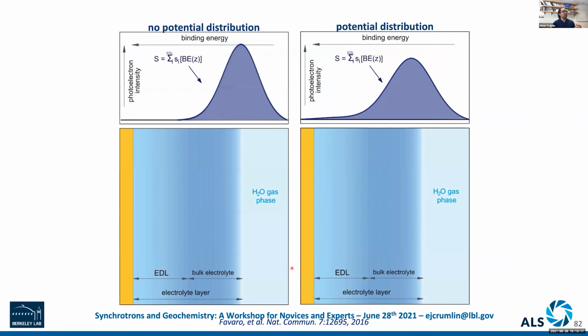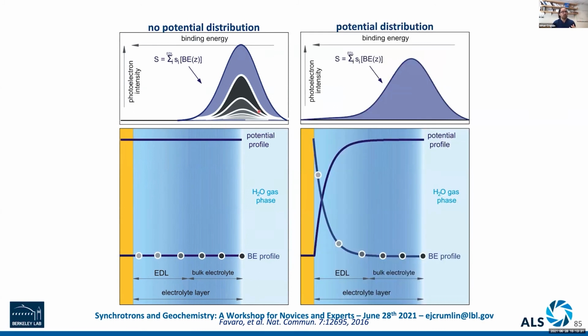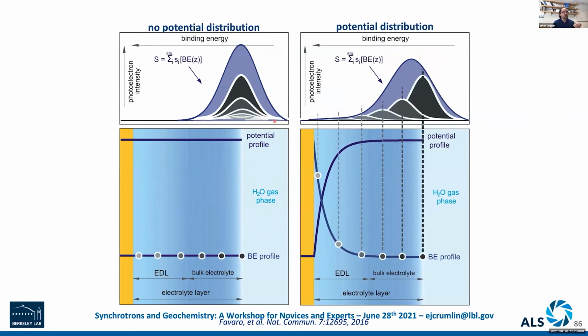We'll do this by effectively looking at the change of the peak shape. If you have everything grounded and you're at the potential of zero charge, all the species you get will sum up to give you a large, sharp peak. But if you have a distribution across that, what you're going to get is actually a broad fat peak. So the width of that peak can give us the potential distribution information.